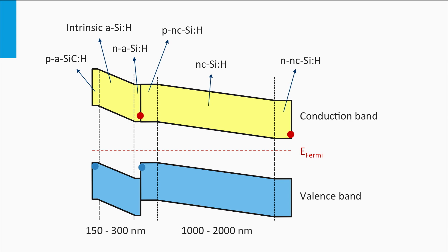Similar to the III-V multijunction, the electrons and holes have to recombine at the recombination tunnel junction between the n-layer of the top cell and the p-layer of the bottom cell. Often, a very thin and defect-rich layer acts like a tunnel recombination junction here. Here these electrons and holes recombine.